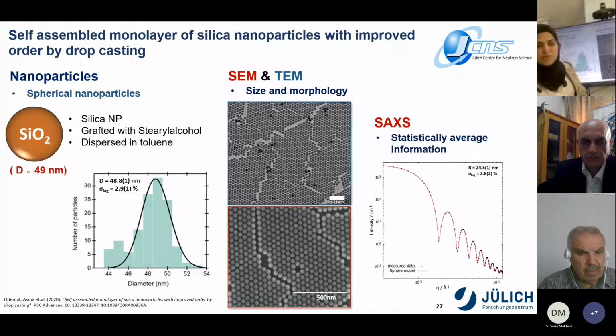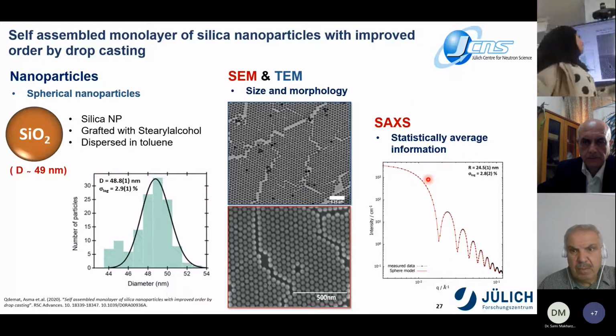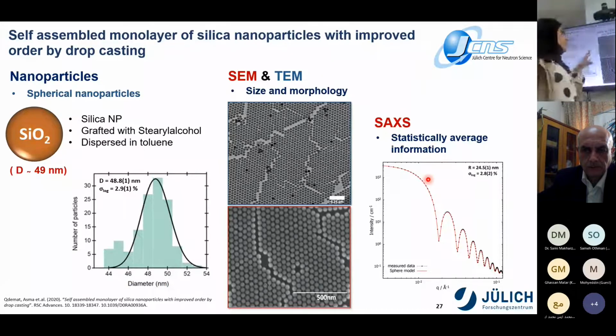Furthermore, I measured small angle X-ray scattering for this particle at Galaxi in order to obtain statistical average information. Here we can see the SAXS curve, intensity versus Q, which shows a very nice curve oscillation, which is an indication of good monodisperse particles. The SAXS data were fitted assuming a spherical form factor, and we end up with a diameter and size distribution which are in good match with the results obtained from the analysis of the SEM and the TEM images.